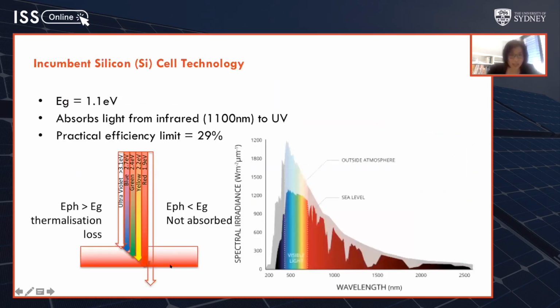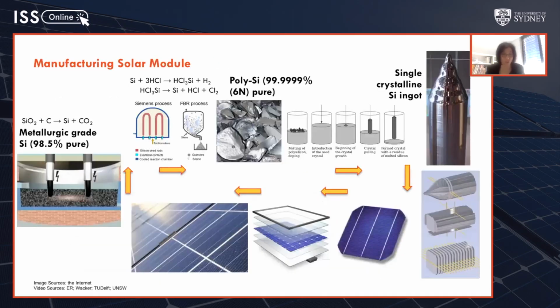Now, the incumbent technology, the solar cells in the solar panels on your roof, are made of silicon, and they have a band gap of 1.1 eV. That means they're very good at absorbing sunlight from near the infrared all the way up to UV. So infrared is around 1,100 nanometers. For photons that have energy higher than that, for example in the UV region, silicon will still absorb them. But as I've said, there will be thermalization loss. Therefore, the practical efficiency limit of silicon is around 29%. So I want you to remember that if photons have energy that is way higher than the band gap, you get thermalization loss.